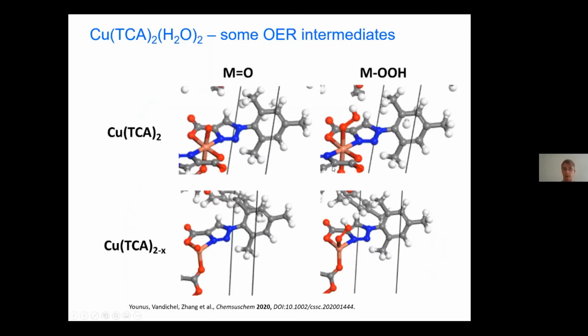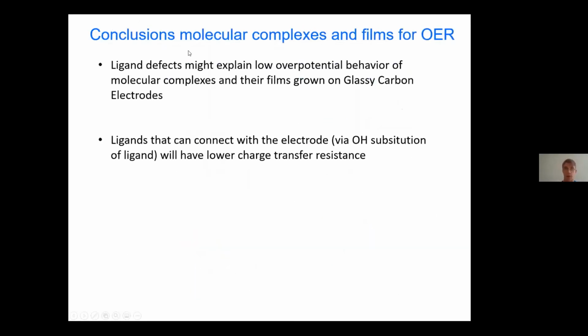So here you see if we have no defect, then the active site is actually 6-coordinated, but if we would have a defect, then the active site is 4-fold coordinated in case of metal oxo and metal OH species. So some conclusions for these molecular OER complexes: ligand defects might be very important. Also, OH substitution of one ligand might be an important factor to lower the charge transfer resistance.